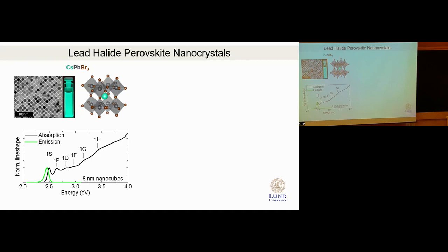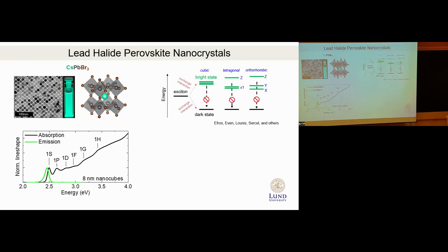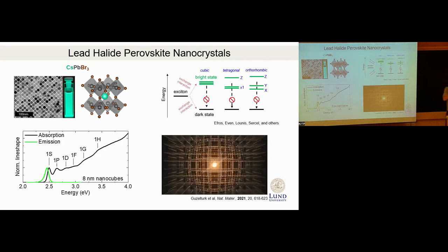So why are these materials better or different from cadmium selenide, for example? Two main reasons, I believe. One is their peculiar electronic structure, which changes depending on the symmetry of the lattice, and there is a debate going on about what is the lowest energy state. But it seems like the community is converging that the lowest energy state is a dark state, and the relaxation from the higher-lying bright state is for some reason inhibited, perhaps by multi-phonon processes. That's one thing which makes them very efficient emitters, especially at low temperature.